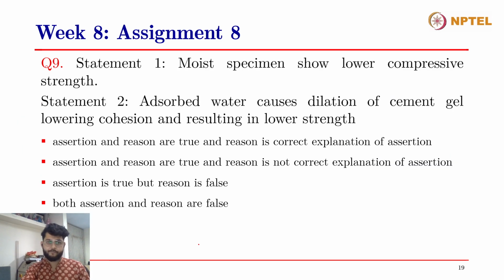And if you compare that to the modulus of rupture test, which is the flexural strength test, only the bottommost fibers across the whole width of the beam are being subjected to the maximum tensile force, and therefore the volume involved in the tensile strength test is very less, and therefore modulus of rupture gives you a much higher value than the other two strength tests. All right. So the correct answer to this question is the first option.